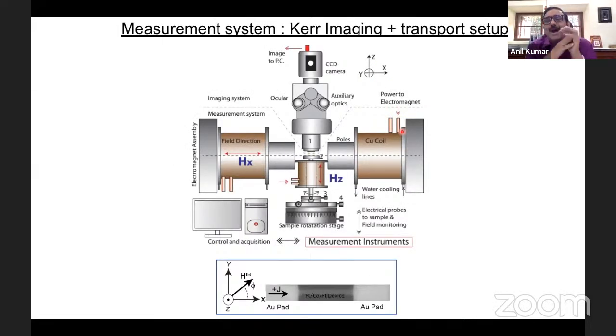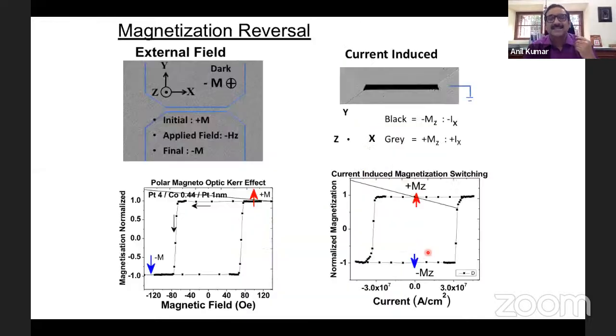And now to show you how this magnetization reversal happens, I told you about the magneto-optical Kerr effect. Now I can do magneto-optical Kerr microscopy. That means like a microscope, I look at the reflected light coming from different regions, and by mapping the rotation of that, I can map the magnetic domains of this material. So this is what I'm going to do here. And also, since I wanted to do current-induced magnetization reversal, we also have an electrical setup attached to this one to apply electrical current and see the magnetization reversal.